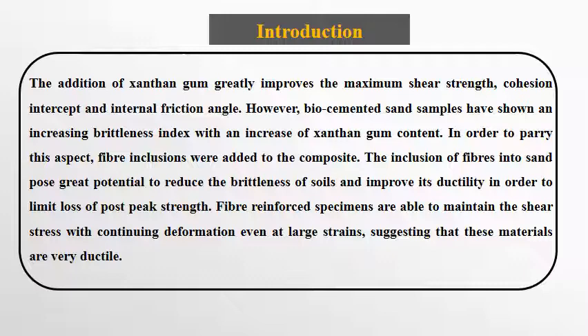The inclusion of fiber into sand poses great potential to reduce the brittleness of soils and improve its ductility in order to limit loss of post-peak strength. Fiber-reinforced specimens are able to maintain the shear stress with continuing deformation even at large strains, suggesting that these materials are very ductile.